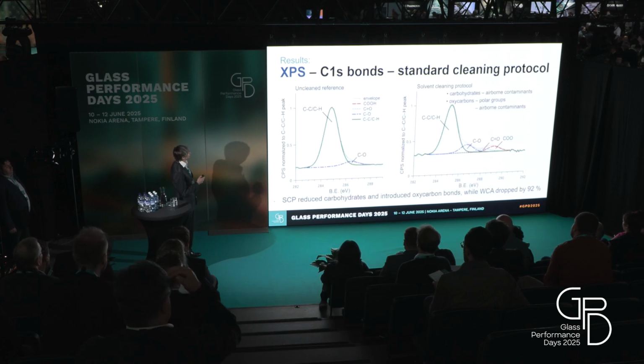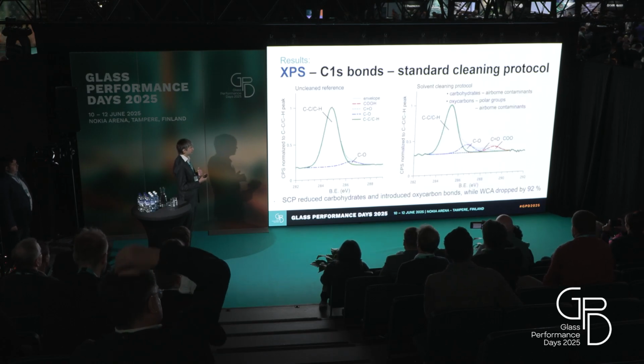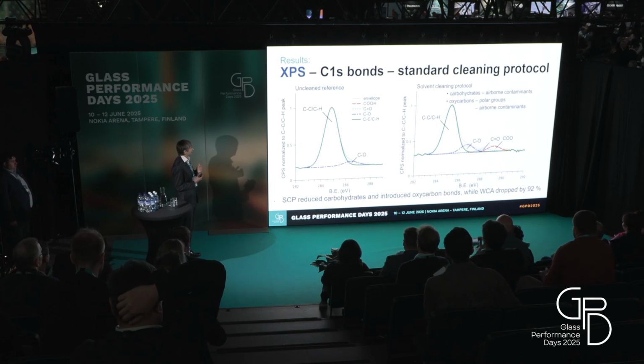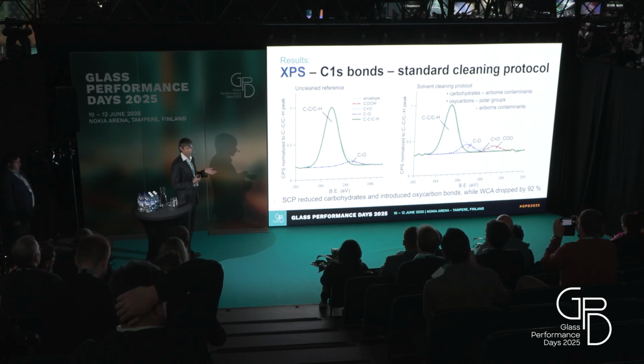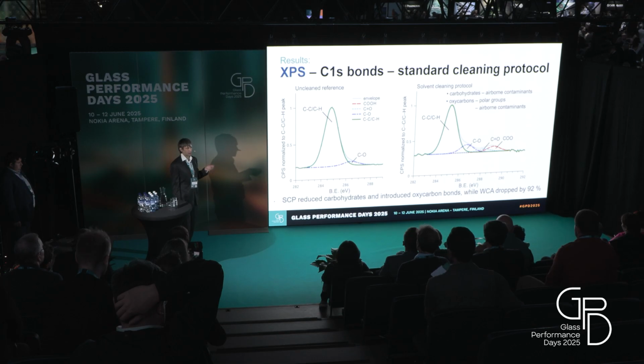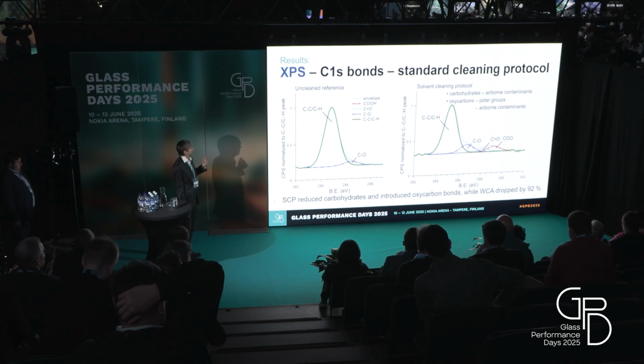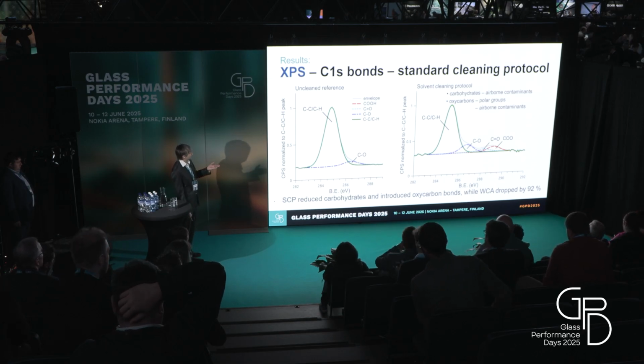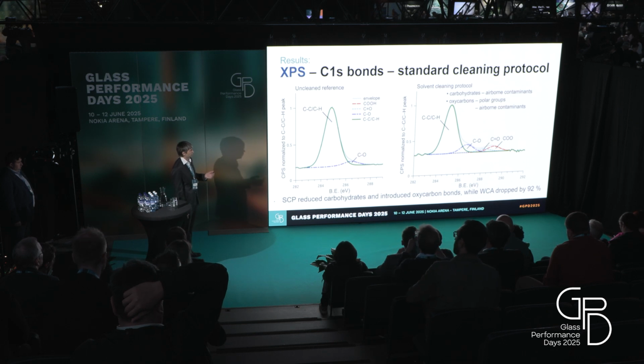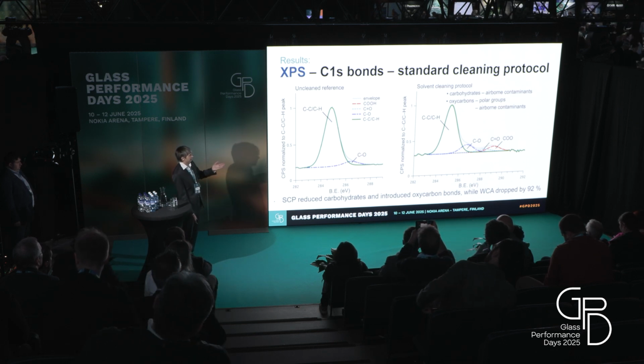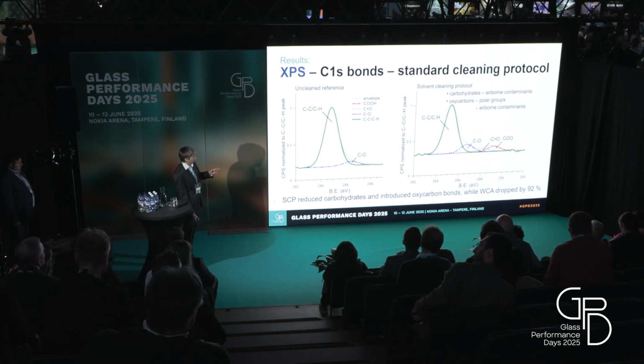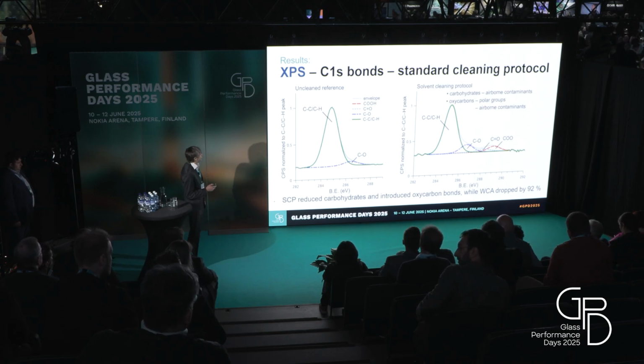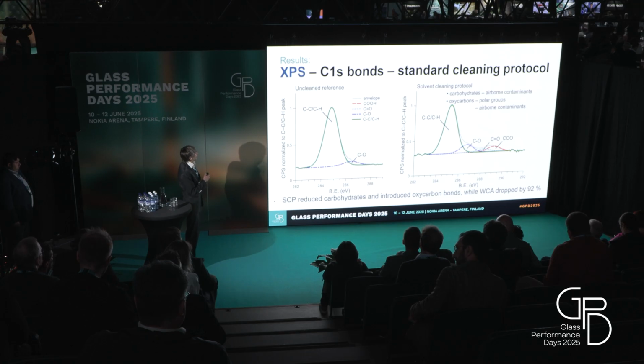So we also analyzed the changes in the bonds of this carbon, to see how it compares to the solvent cleaning protocol, which we used according to the recipe from our chemical colleagues. So this also increased the polar groups, which are indicated by carbon and carboxyl groups. And we also decreased the carbohydrate peak, which is the green one.